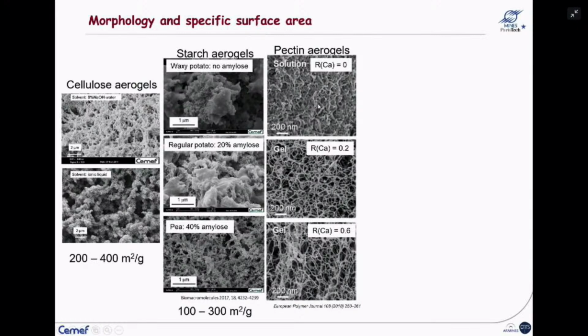And probably the most beautiful case is pectin aerogels. Here are the examples when pectin, here the starting is a solution without any cross-linking. And here are the two examples when pectin was cross-linked with calcium a little bit and more. So the network was formed, and with a very fine network structure.